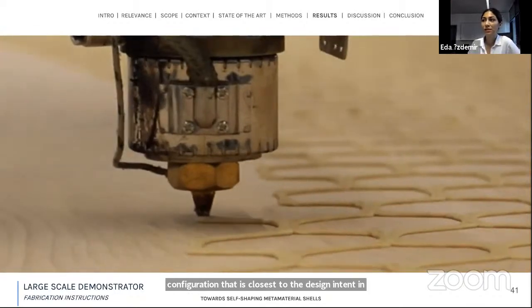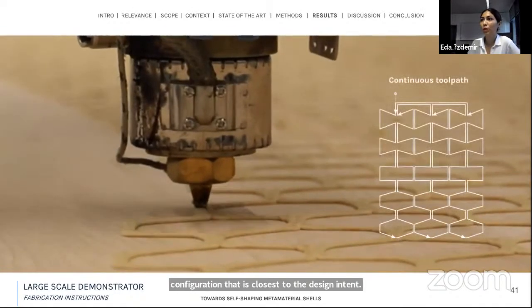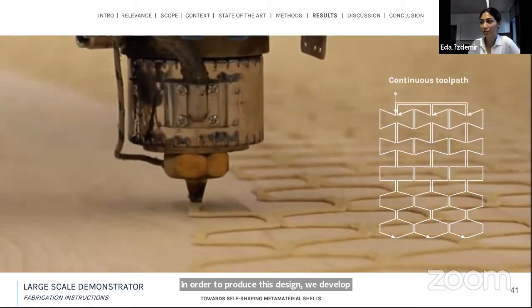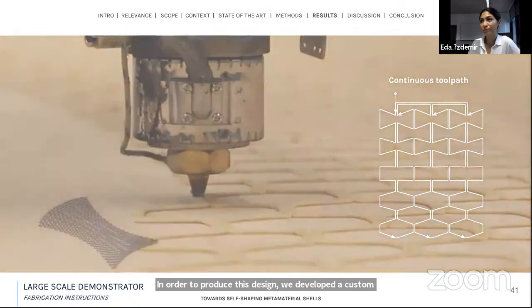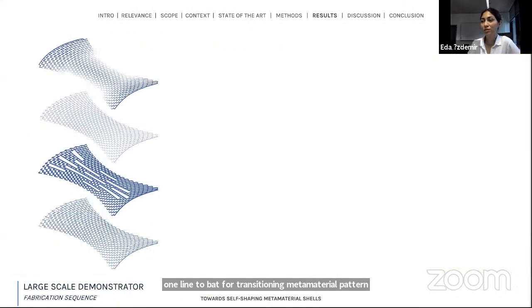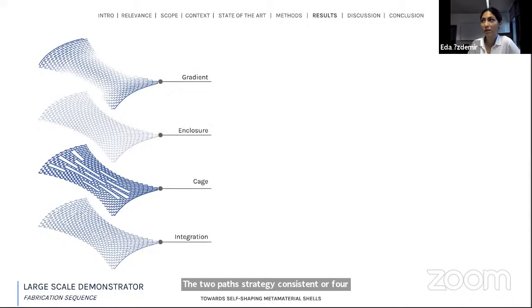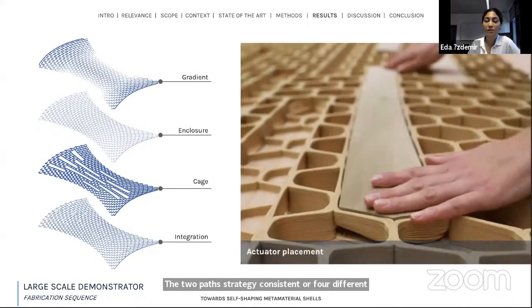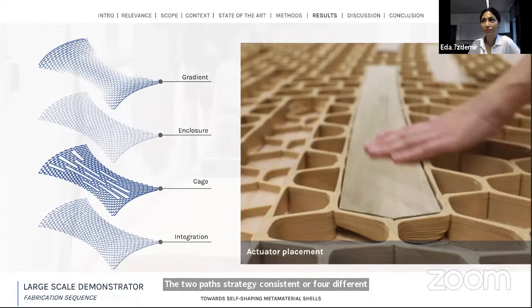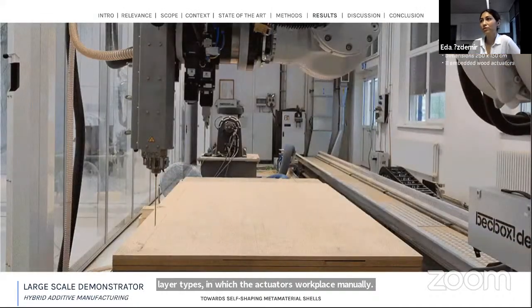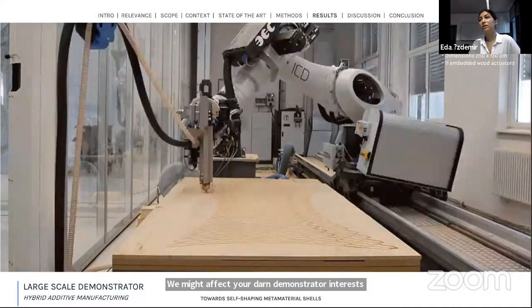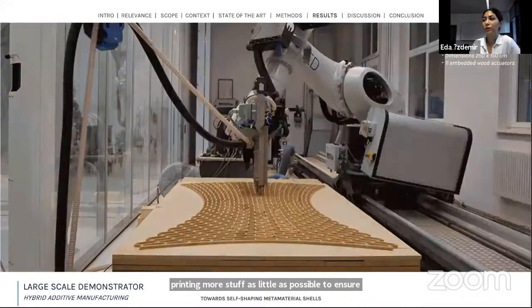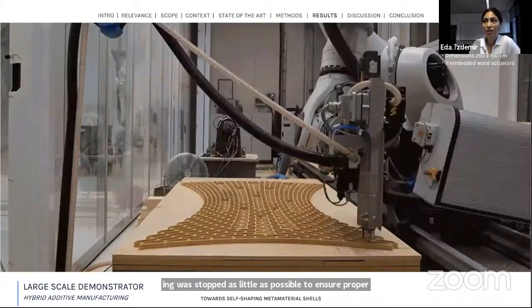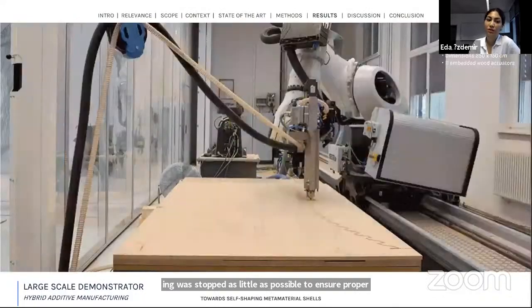In order to produce this design, we developed a custom one-line toolpath for our transitioning metamaterial pattern. The toolpath strategy consisted of 4 different layer types in which the actuators were placed manually. We manufactured our demonstrator in 15 hours. The printing was stopped as little as possible to ensure proper bonding between the layers and to avoid the bending of the actuators before the end of the production process.